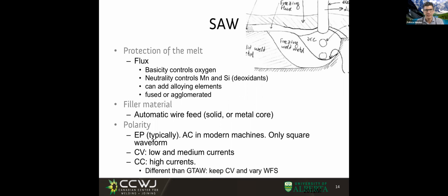With agglomerated fluxes, when they melt and turn into slag, the solid slag, we can also try to crush it, and many people try. But the agglomerated fluxes tend to have more reactivity with the melt. They can have different basicity, different neutrality, and add or take away silicon or manganese. So with agglomerated fluxes, people try to either not recycle those or recycle them in very small parts inside a batch of new powders.